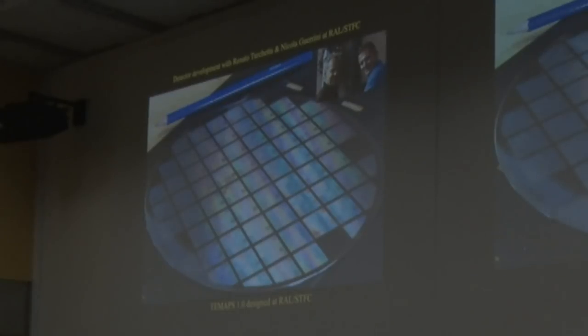So this was an early 8-inch wafer with test structures, lots of them. So that's a detector. It's got 25 different areas. They picked which ones were better, which ones were worse, and then eventually made a detector that would be one of them, and it's now had most of the silicon in that wafer, 700 microns thick, removed, and it's been back thinned down to 30 microns thick. So it's like a thin piece of paper, actually. You can bend it, and it still works. And the high-voltage electrons hit the detector, and they go straight through, leaving a very, very sharp, fine track for where the particle was. So much cleaner, much better, much higher resolution signal with much lower noise level than you get on film.